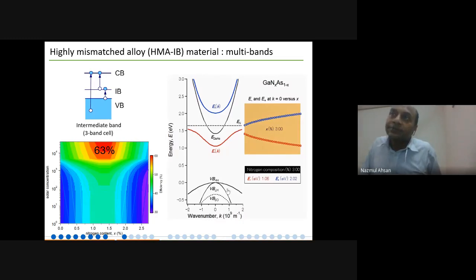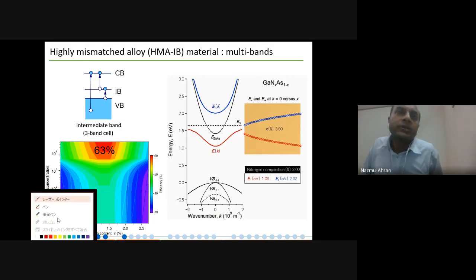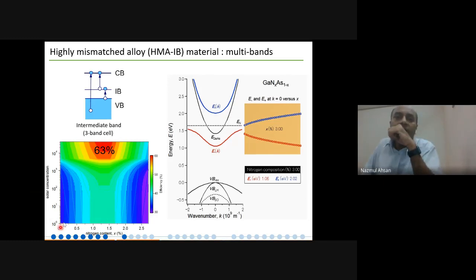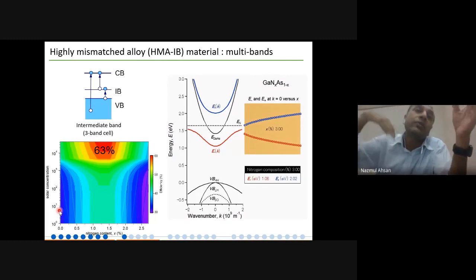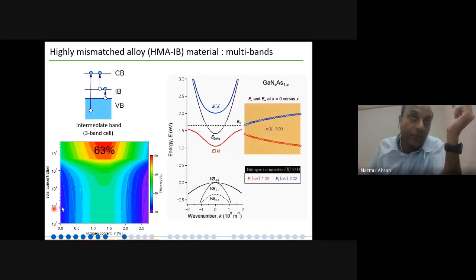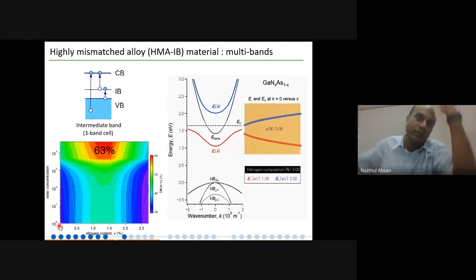And now I'm talking about the band gap. Now here, let me go here. Right here, in the horizontal axis, I'm changing the same nitrogen concentration, 0% to 3%, 2.5% here. And in the vertical axis, I told you at the very beginning that we can concentrate the sunlight, and gallium arsenide is a very expensive material. At the same time, with this kind of material, theoretically, if you concentrate the sunlight, you can increase the solar cell efficiency. So we do have a dual effect. So what I'm doing, I'm concentrating the sunlight from one sun. One sun means no concentration, just the single sun we have on top of our head. But if you concentrate 10 times here, 100 times here, 1,000 times here, 10,000 times here, this is a log scale.